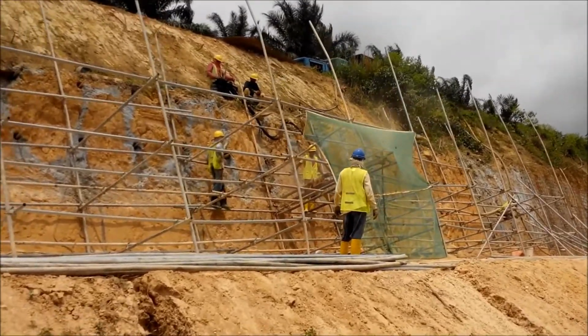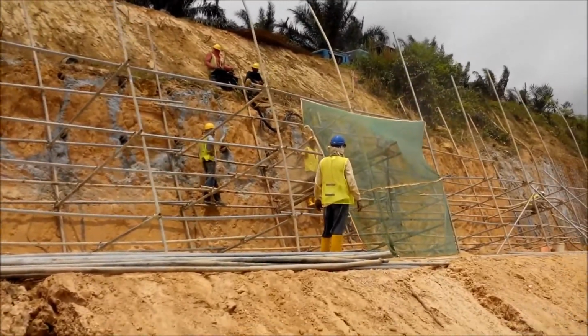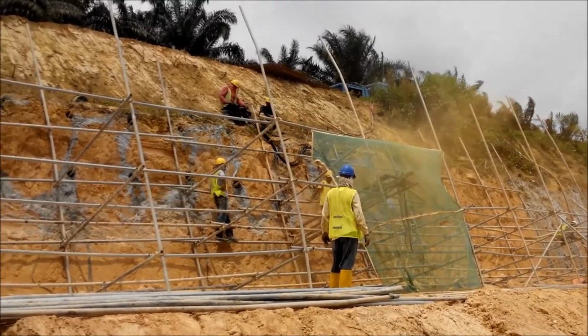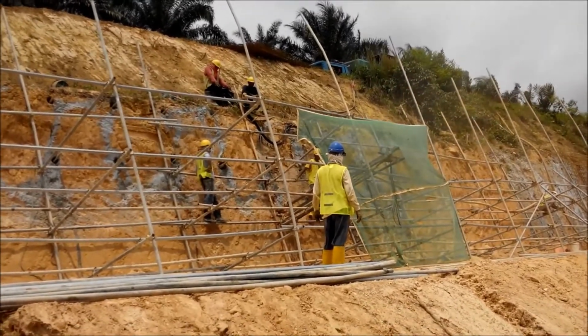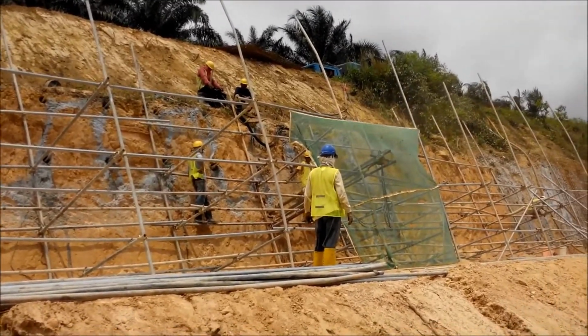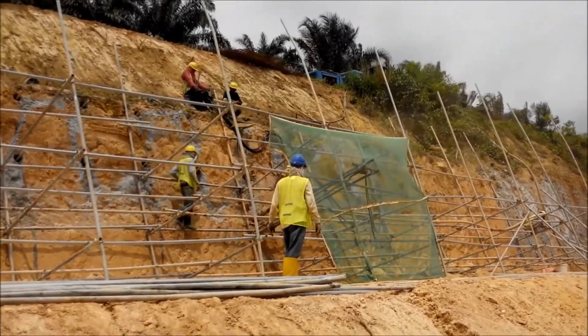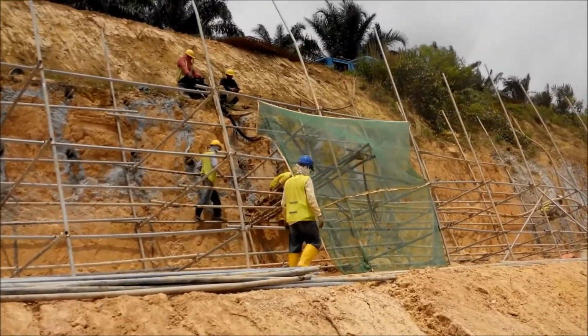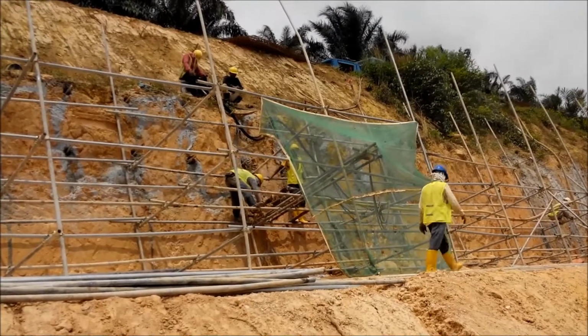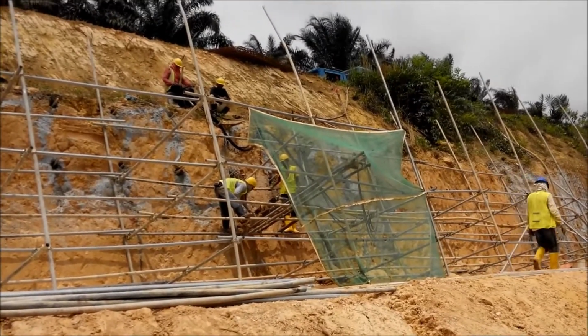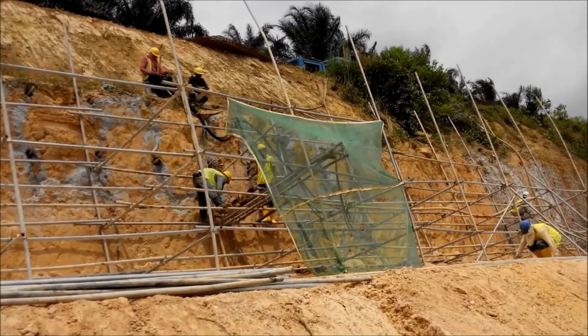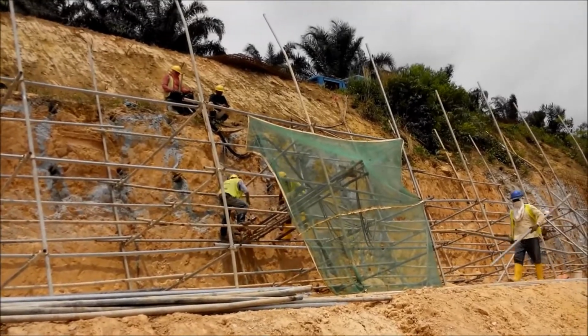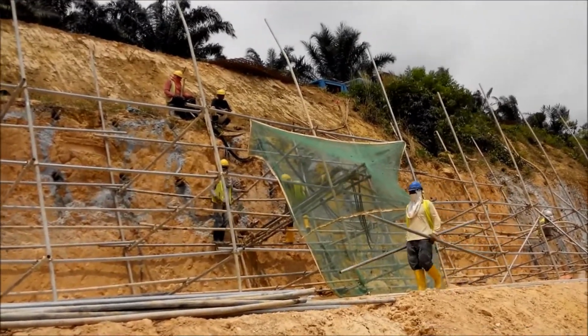Typical guniting slope protection should consist of a minimum 75 mm to 100 mm thick sprayed cement and sand ratio with a layer of A4 or A6 wire mesh. Those reinforcements function to reduce shrinkage and thermal cracking. Guniting, if properly designed, constructed and maintained, can preserve the soil suction, which can be a great contributor to slope stability.